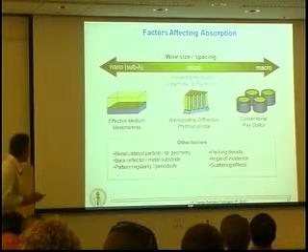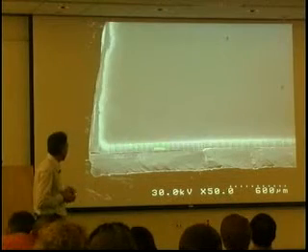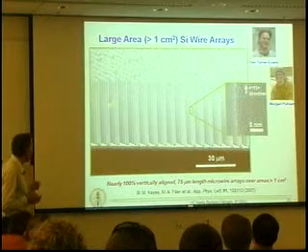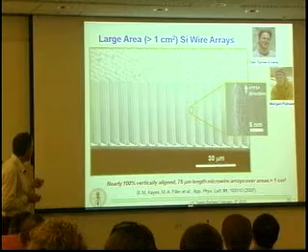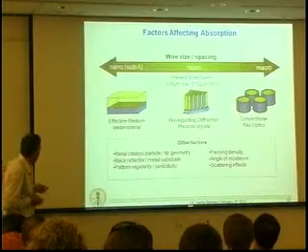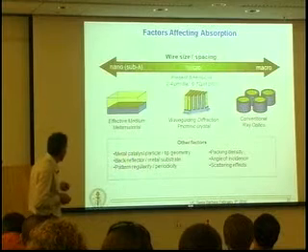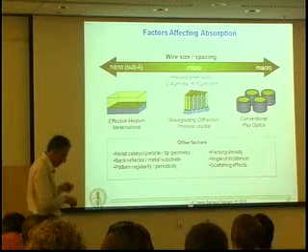So that's where we are at the moment. So another aspect of this is the question of whether or not when you make a dense array like this, do you in fact absorb all the light? When you look at this array, actually it doesn't turn out to be that dense. If we look down on the substrate, the area of the substrate that we subtend is only 5 to about 15% of the projected area.